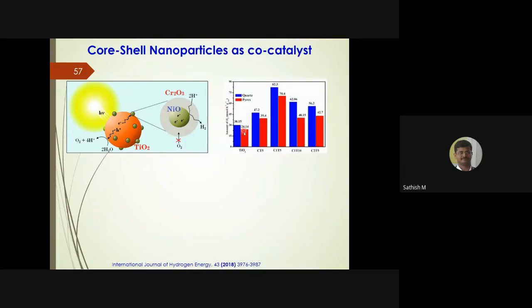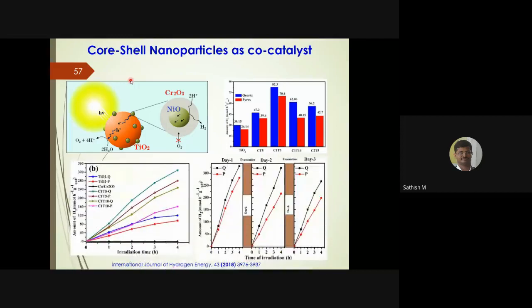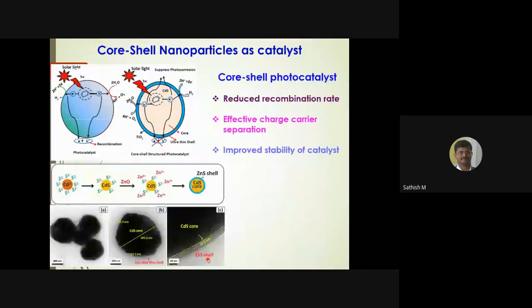So if you could see here, in the previous case I just put some micromoles. Here you could see this is millimoles, and it is per hour. It is maybe close to 80 millimoles per hour, whereas in the previous case we observed only 600 micromoles per 6 hours or 7 hours. So this is a kind of improvement over the last 10 years. We could have this kind of systems.